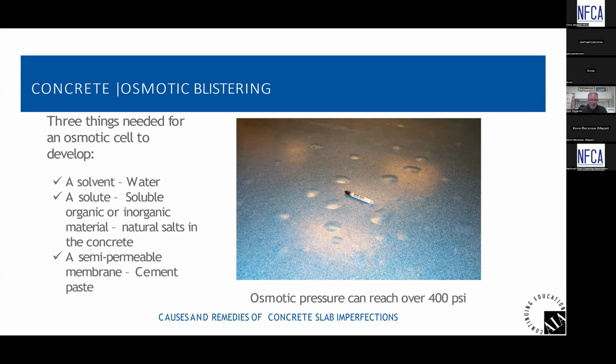And concrete has salts in it. There's natural sodium, potassium, chlorides, sulfates in concrete. They're in there all the time. They're low parts per million. They never hurt anything. They're just in there. But if we have a lot of excessive moisture, sometimes maybe salts are coming from the ground, depending on the application. Maybe they're coming topically based on the use of the area. But if we have salt levels, if we have a water source, and we have a semi-permeable membrane, that is the three things needed for an osmotic cell to develop.